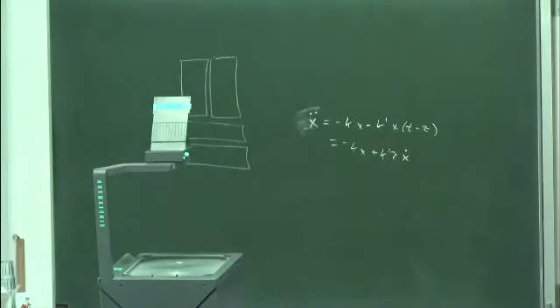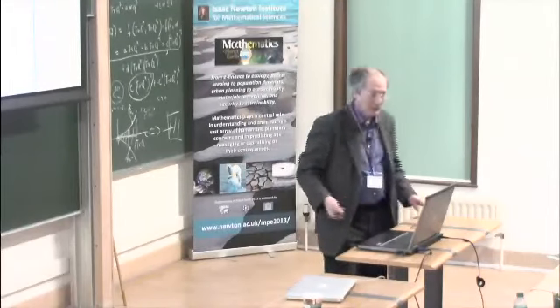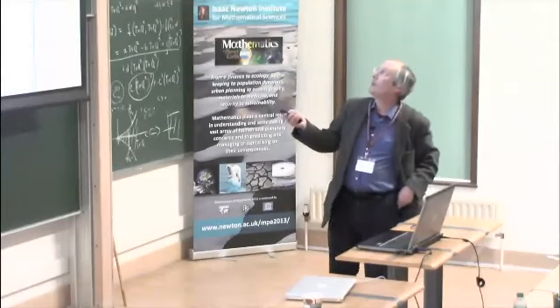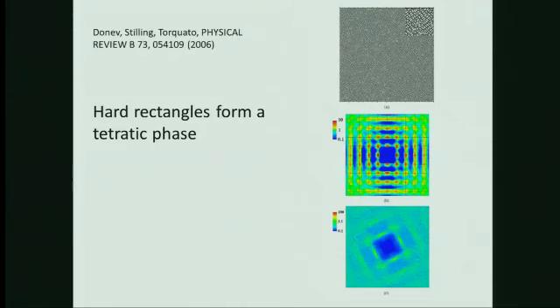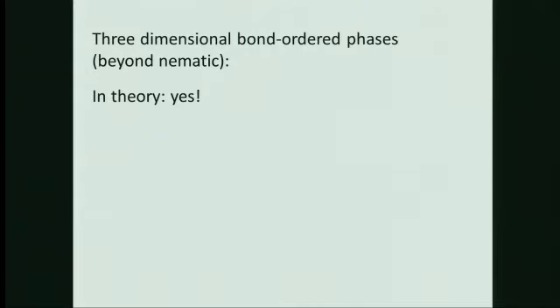And in this particular case, there was work by Donev, Stillinger and Torquato, where here you see a blow up, you see these things. They're not always, sometimes you see a whole row of them, but they computed the g of r diffraction pattern, and they see a 4-fold symmetry in the diffraction pattern, which suggests that actually this is a phase with 4-fold bond order. So in this case, there seems to be clear evidence that you'll have bond order in a 2-dimensional system. Now, this is all 2 dimensions.